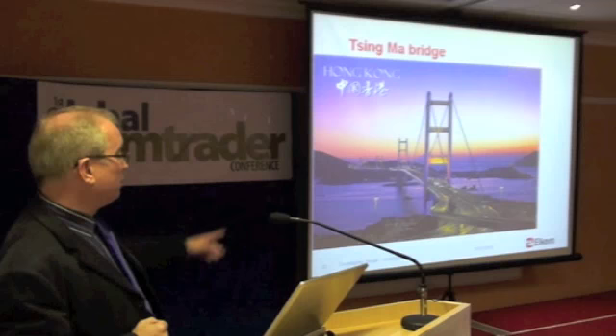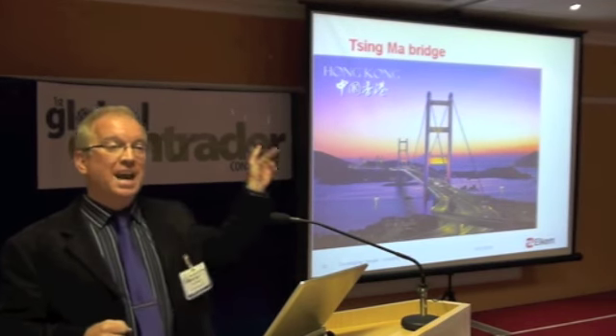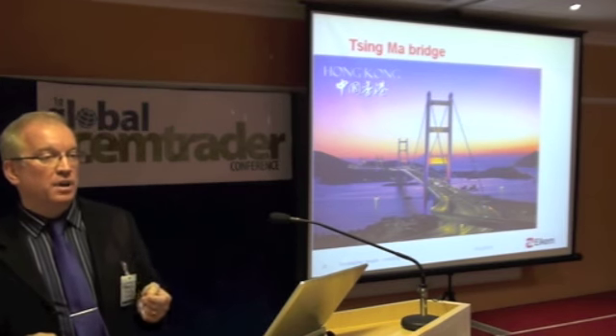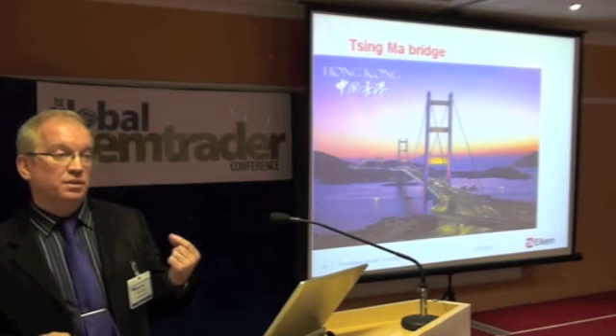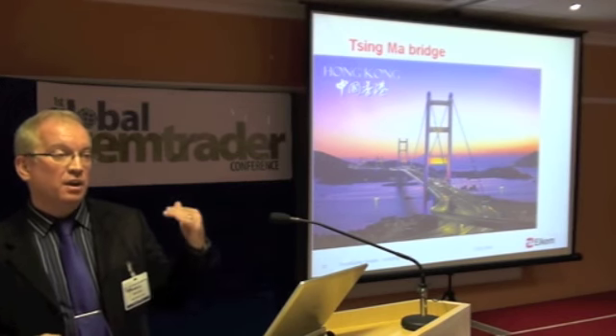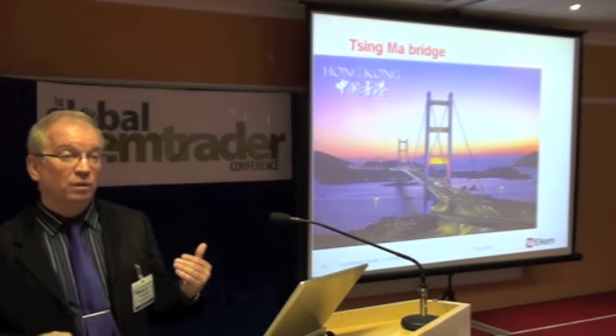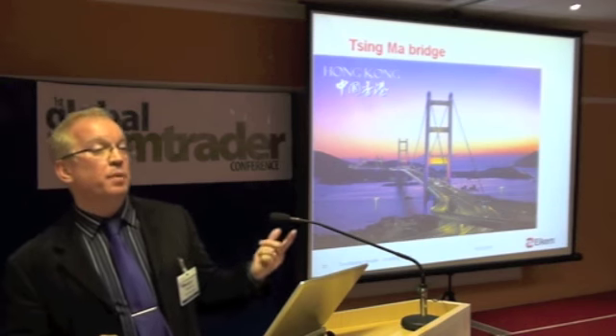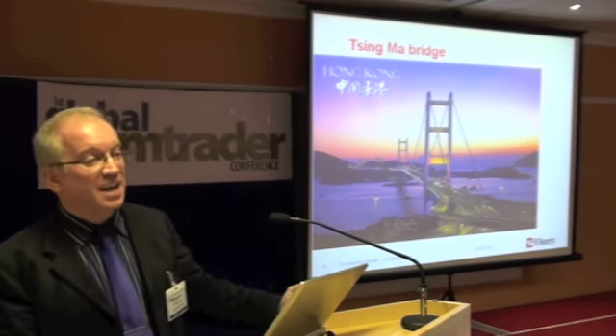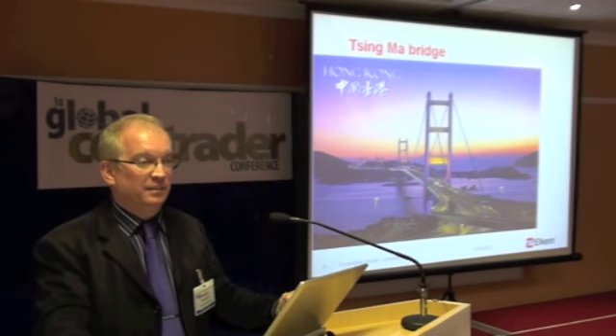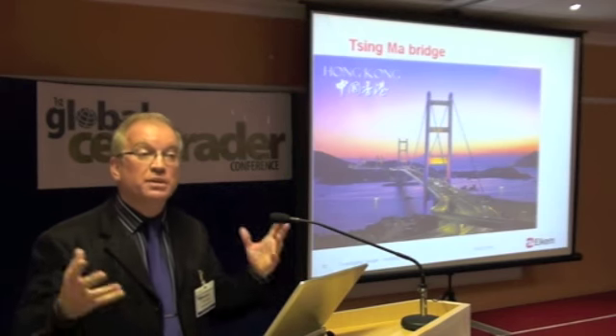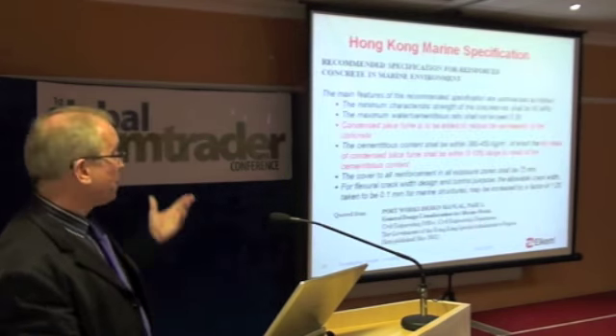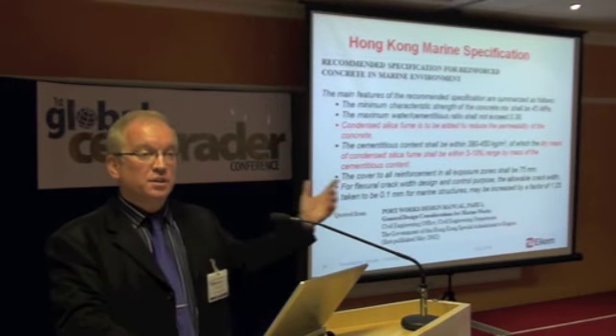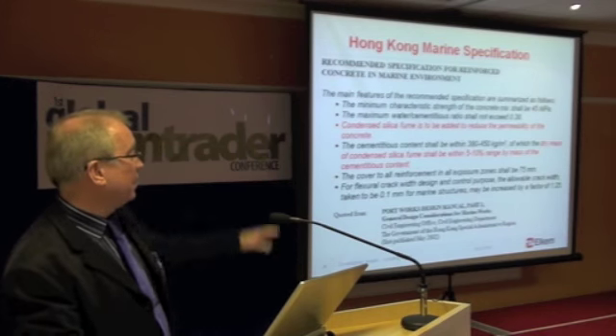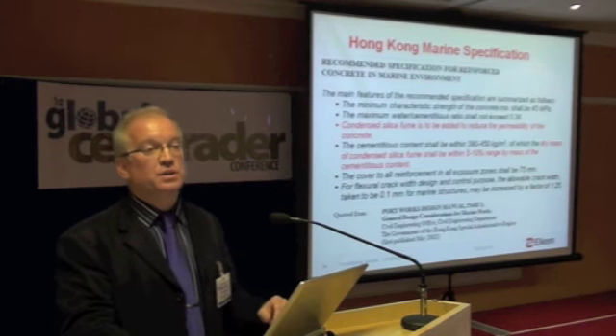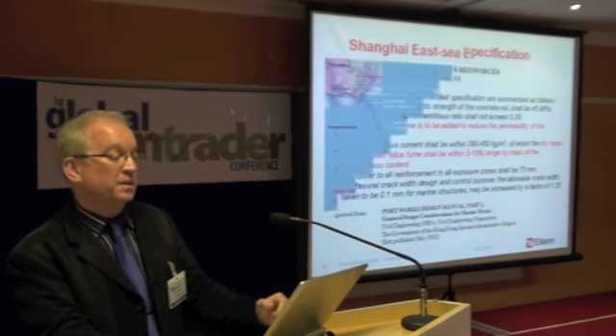OPC, fly ash and silica fume for the main abutments, main areas that you can see, but the towers are 65% blast furnace slag, 30% Portland, and 5% silica fume. Believe it or not, that mix at only 390 cement content, total cementitious, achieved over 100 megapascal in long-term strength. The chloride resistance was 10 to the minus 14. That's incredible durability. But because we designed for it, we were able to achieve it. And of course, Hong Kong then took it on. This is the specification for the marine environment. You just need the red lines, 5 to 10% by mass of the cementitious product to get that impermeability.